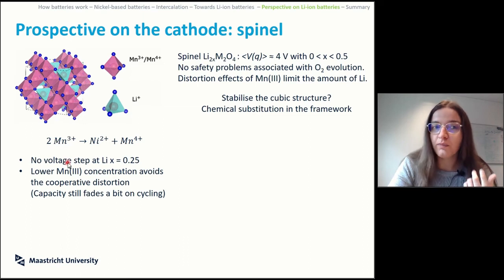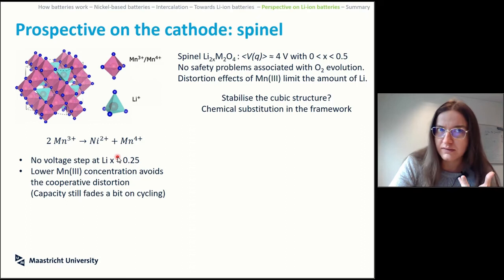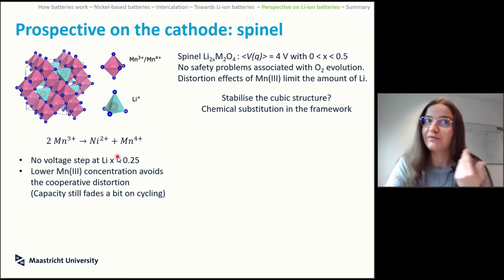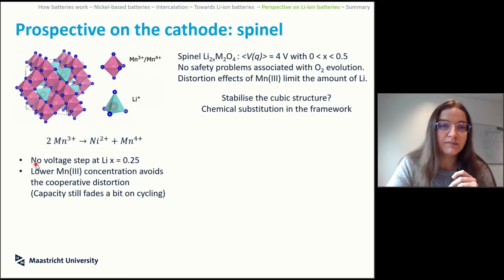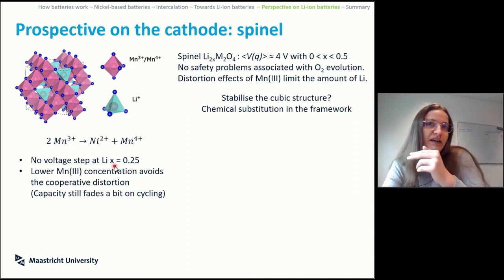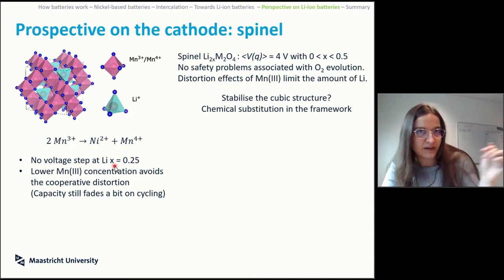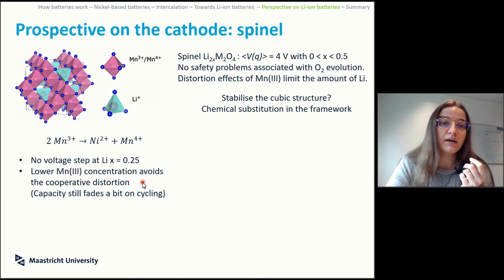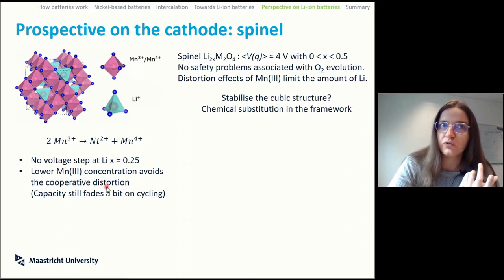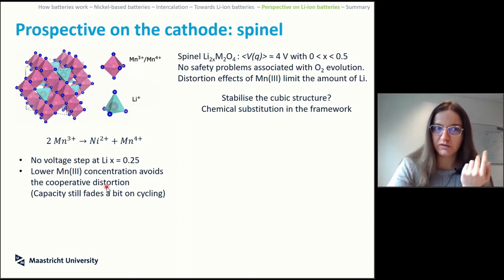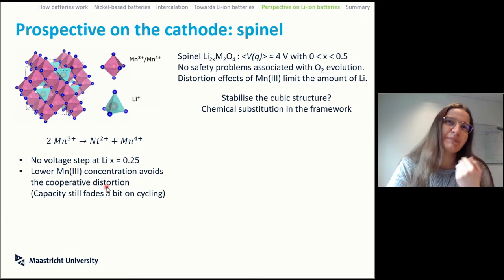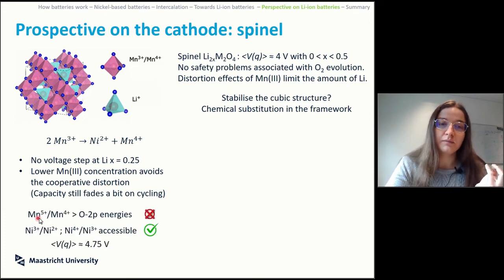So for 2 manganese 3 plus, you can have a nickel 2 plus and a manganese 4 plus. The manganese 4 plus doesn't have the problem of distorting. There is not this teeny tiny voltage step at 0.25 as the regime changes. Since you have a lower manganese 3 plus concentration because you doped with nickel, you don't distort the whole structure because of this Jahn-Teller thing. The capacity will fade a bit upon cycling.